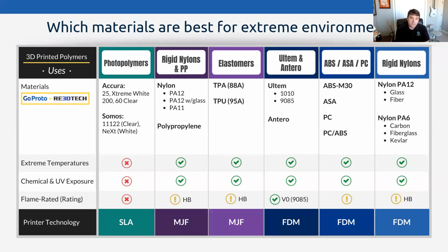And then ultrasonic welding, great question. Yeah, MJF works great for ultrasonic welding. The other processes, not really, because of the way it builds. But MJF works phenomenal for ultrasonic welding. We've had several customers ultrasonic weld PA12 parts. Now, we haven't had anybody do it on other materials that I'm aware of, but the unfilled nylon 12, they've done it. They've ultrasonic welded parts, and it's worked great. Treated just like regular nylon plastic.